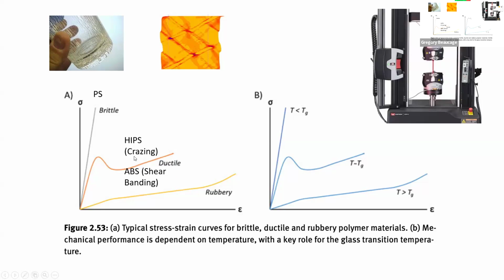So if you have a lot of crazes, they're smaller, so they don't break. If you have one craze, it gets large and breaks. That's the idea. So the idea is to dump the rubber in to make a lot of defects in it that craze a lot, and then it absorbs a lot more damage before it fails, which turned out to be true. I think they made the material and they figured that out. It wasn't like they said, oh yeah, we could do this, let's try it. It was more like, let's see what we pour in the pot, what comes out, let's make a Dixie cup. Oh, it doesn't break, I don't know why. And they kind of sorted out why.